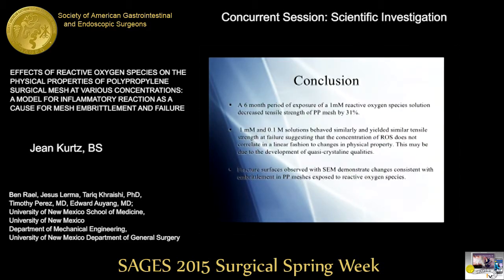So our conclusion was that after a 6 month period, which is relatively not a very long period of time, at a physiological concentration of 1 millimolar, we did observe a change in tensile strength of polypropylene mesh that was decreased by 31% compared to out of the package mesh. We also noticed this nonlinear behavior, so that the concentration didn't correspond linearly to the amount of change in tensile strength. And we think this is because it's taking on this quasi-crystalline property. Fracture surfaces observed in scanning electron microscopy were consistent with this idea that the meshes are embrittling.